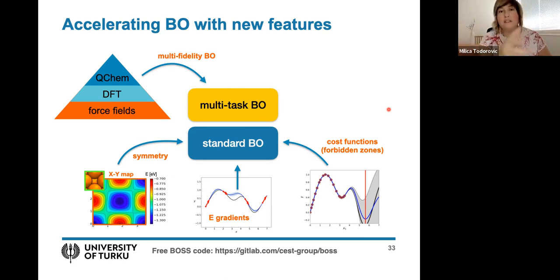And what we're doing here is the inverse. We are fixing the building blocks and we're doing many of these informed single point calculations, and then we get these approximate landscapes that tell us which regions are promising and which aren't. And then in all the local minima, we do the relaxation only from the local minima. So we limit the number of structural relaxations that we do on purpose to only the regions where we think already the energy is low, and these are then the promising local minima and the promising solutions. Okay, does that answer your question?